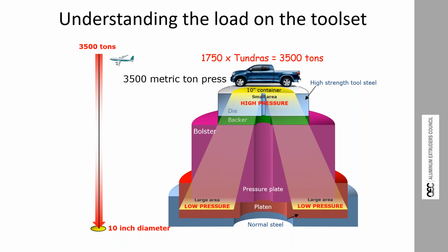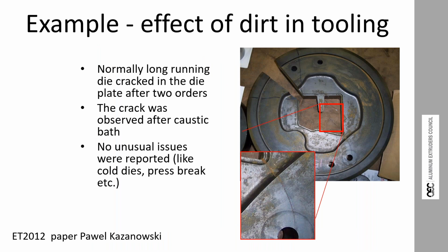It will dent it. You can coin the front of the container. You can do a lot of damage with these things. And here's my example. This is taken from an ET paper, 2012, from Pawel Kazanowski, who was working for Wafer at the time. This is a die plate for a GM bumper die that was running at the hydro facility in Holland, Michigan. And you can actually see down here, fairly clearly, there's a crack in the die plate. And there was another crack up in this corner. And you can see where we cut it out to do some metallurgical investigation.